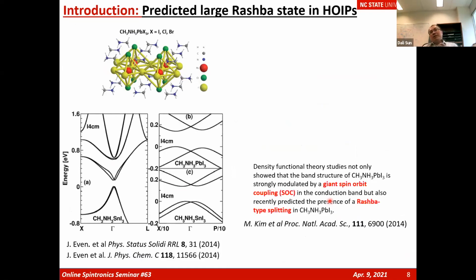Because of the prediction of a large Rashba effect, because of the heavy metal lead in such a hybrid crystal structure in the octahedral layers, the lead induces spin-orbit coupling, and the inorganic-organic hybrid structure induces inversion symmetry breaking. By DFT calculations back in 2014, people predicted there might be a huge Rashba splitting effect in these photovoltaic materials, which had not been reported before.